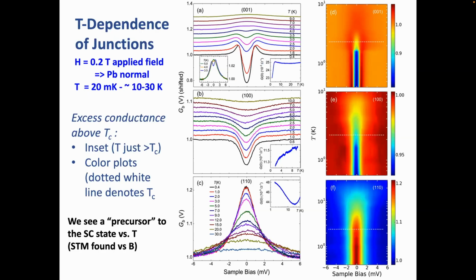So what we have here, we didn't do the color plots only to get it into a high impact journal, because they're actually fairly helpful for understanding this. The top plot is the C-axis direction, the middle plot is the 100 A-axis direction, and the bottom plot is the 110 or nodal direction.